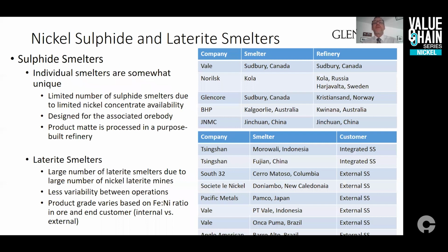The nickel sulfide smelting industry is characterized by a small number of processing plants that were designed specifically for the associated ore body. Many of these smelters have exhausted their maiden deposit and have adapted to treat either new ore bodies or purchased concentrates. Each smelter is typically tied to a purpose-built refinery designed specifically for the characteristics of the smelter matte. As a result, nickel concentrate and matte do not have a broad commodity-type market, such as that found in the copper industry. The nickel sulfide industry is presently constrained by the lack of new high-quality ore deposits.